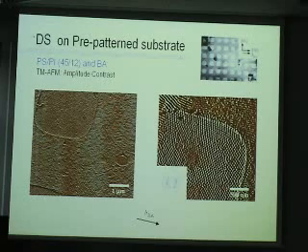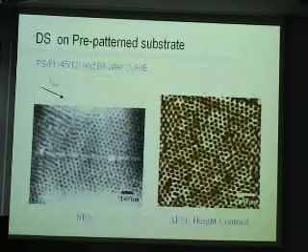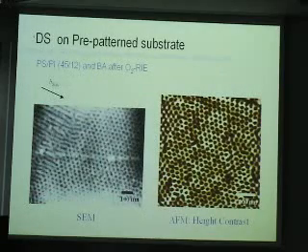After we did the oxygen plasma reactive ion etching, we created the nanometer scale hole structure. Especially, we are interested in the patterned area. This height contrast AFM image shows the dark and the gray contrast in this picture.